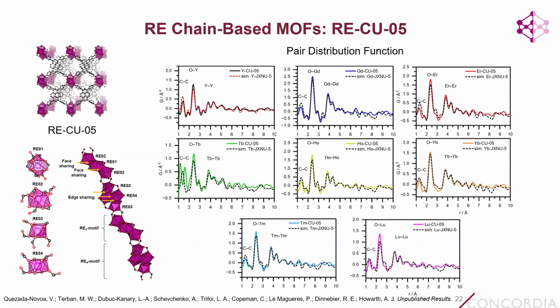So we didn't just look at the dysprosium analog, but we also looked at the pair distribution function data for all of these different analogs of CU-05. And what you can see is that in all cases, the pair distribution function matches quite well with the simulated models for JXNU5 with these different rare earth elements.